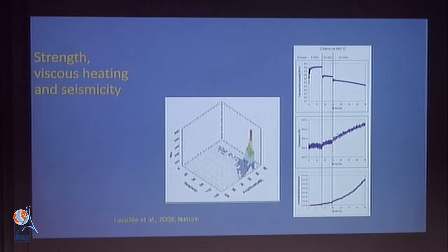You're heating the material. Remember, you don't have to transport this heat. This heat is being generated everywhere where 2 atoms are shearing over each other, so it's actually auto-production of temperature. And so it's immediately at the place where it needs to affect the rheology as soon as it's generated. Okay, it's not being heated from without or something like that. It's not a heat transfer issue about getting the heat in. It is a heat transfer issue about whether or not you can prevent the heat from getting out, of course.